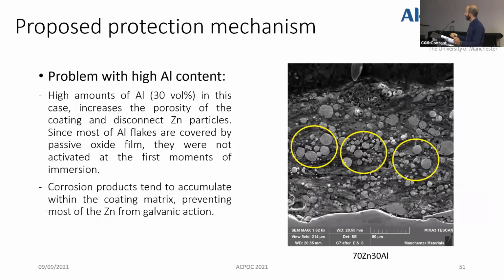The problem with a high amount of aluminum content is that it may increase the porosity of the coating and disconnect zinc particles, since most of the aluminum flakes are covered by a passive oxide film and will not activate in the first moments of immersion. So the corrosion products tend to accumulate within the coating,